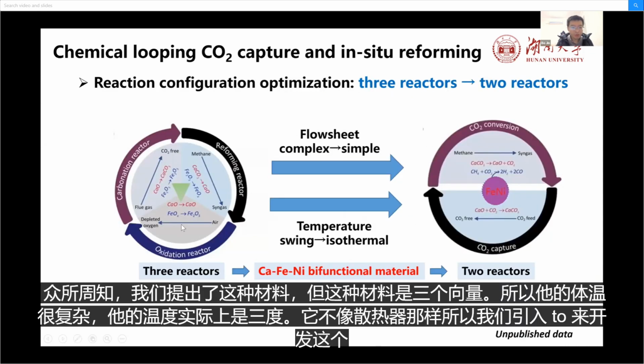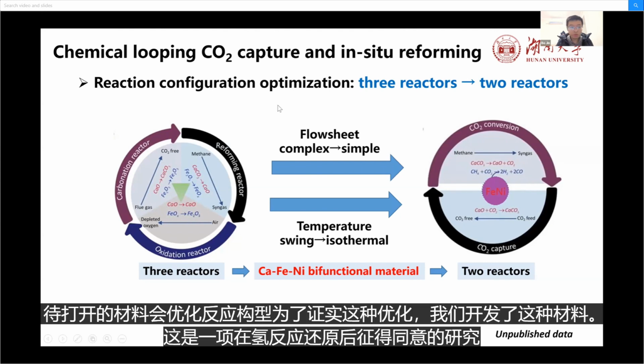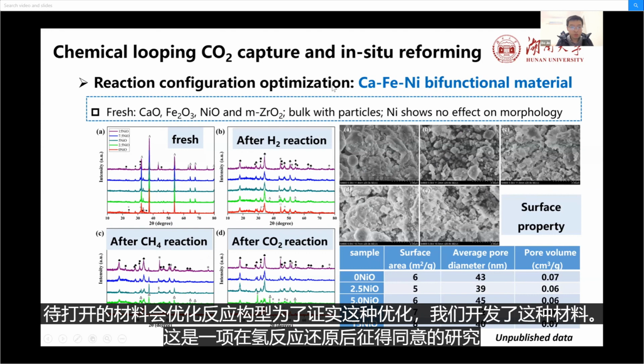As we know, we proposed this material, but this process needs three reactors, so its flow sheet is complex, and its temperature actually is varied. It is not isothermal. So we introduced nickel to develop this calcium iron nickel bifunctional material to optimize the reaction configuration. In order to confirm this optimization, we developed this material.